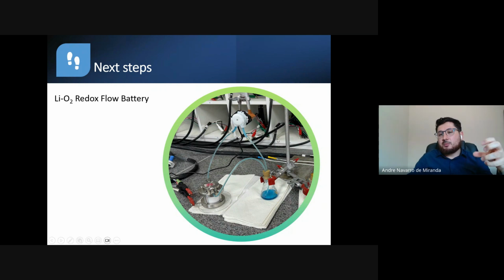So instead of forming the peroxide over the surface of the cathode, we start to form the peroxide in the solution here. So we have a tank in appendix to the battery, and it's interesting that the capacity is not proportional to the cathode surface, but it's proportional to the volume of electrolyte that I have here.